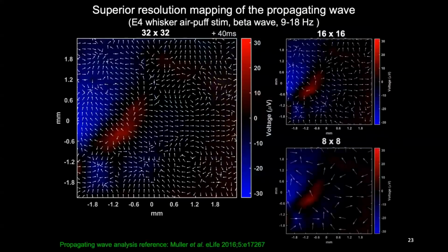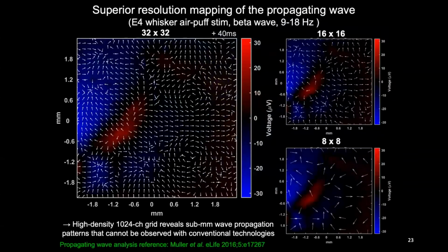Now, having this high resolution is very important, right? You can see the level of details that we can get with the 1024 channels. And if we undersample from the same data in 16 by 16 or 8 by 8, you start to lose some of these wave patterns with the lower resolution.